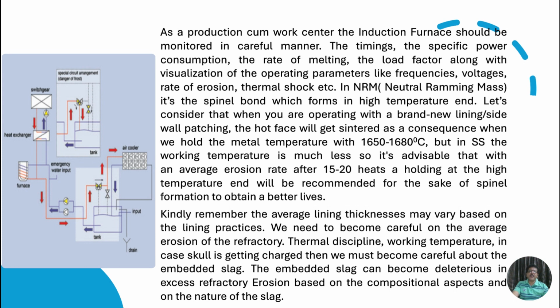In NRM, it's the spinel bond which forms at the high temperature end. Let's consider that when you are operating with a brand new lining or sidewall patching, the hot face will get sintered. As a consequence, we hold the metal temperature at 1650 to 1680 degrees C.